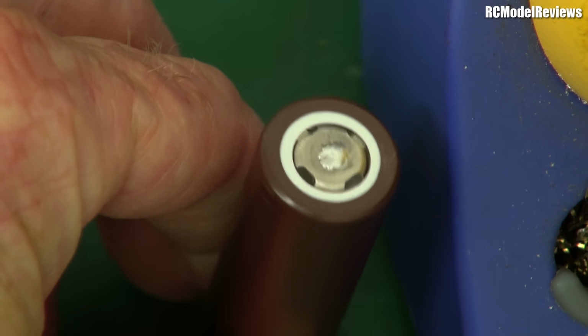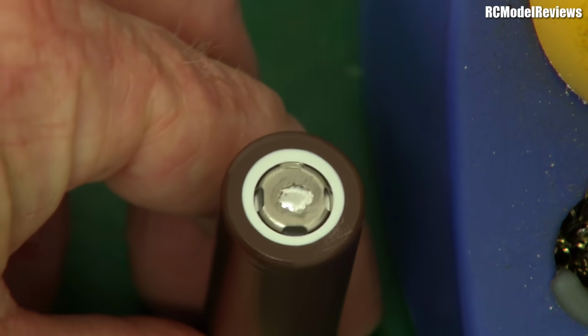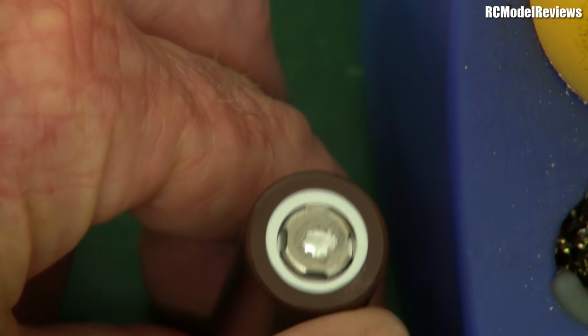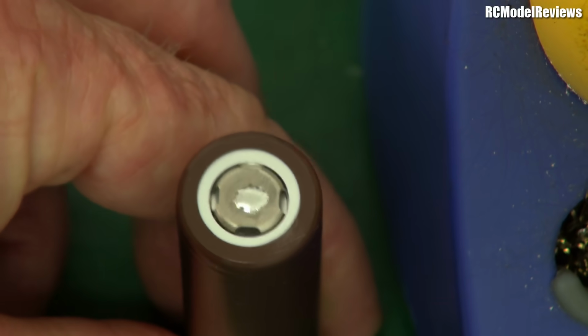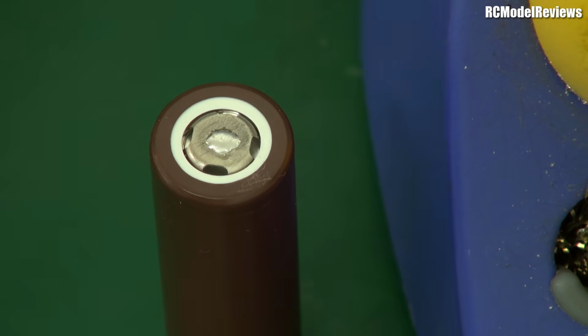See that? See how quick that was? And that's perfectly alloyed. This is not just a blob sitting on the top that's going to scrape off. You'd have to grind that off because that's alloyed. And in a good solder job, the solder itself alloys with the metal underneath. It doesn't just sit on there held on by a bit of flux. It actually creates an alloy at the interface between the solder and the base metal.